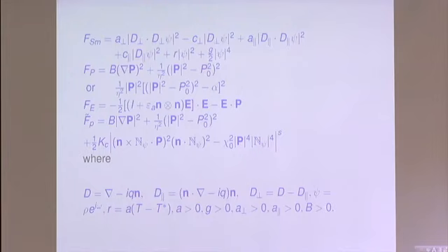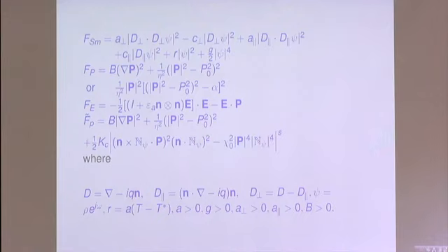Okay, here's the next one. This is the ferroelectric case, and this one I consider antiferroelectric cases. So what happens in the antiferroelectric cases? In each layer the molecules point in different directions. When you look at the average over the neighbors, you get zero, so the continuum P becomes zero. You also consider P equals zero, then we consider antiferro. And then if you have some P of magnitude 1, then these are ferroelectric cases.